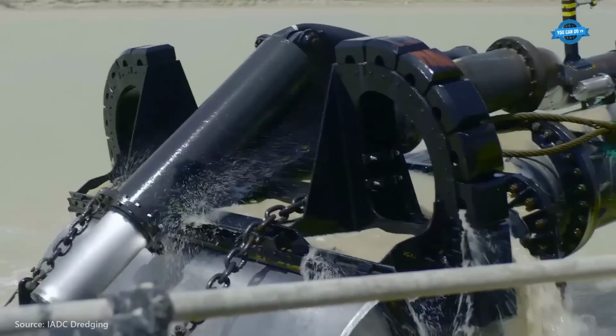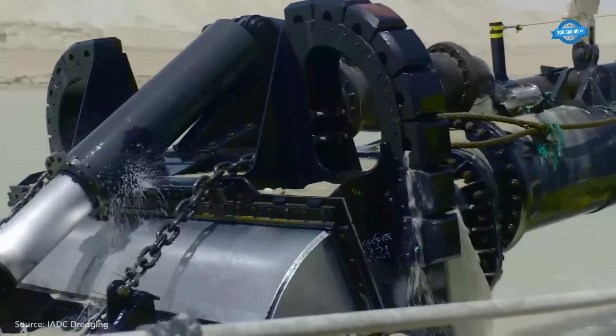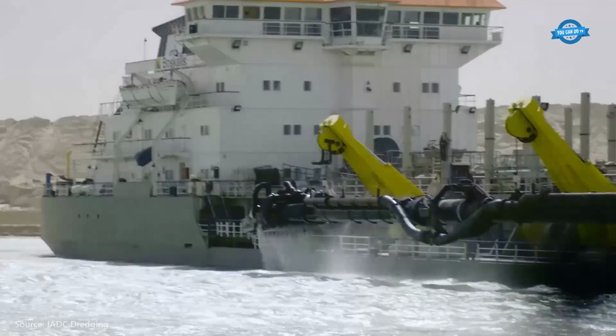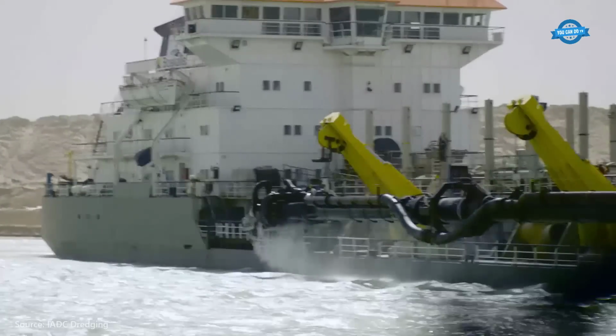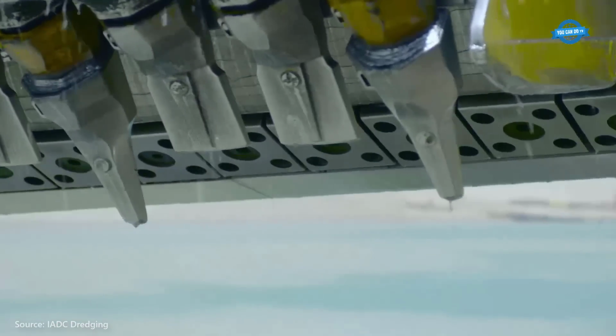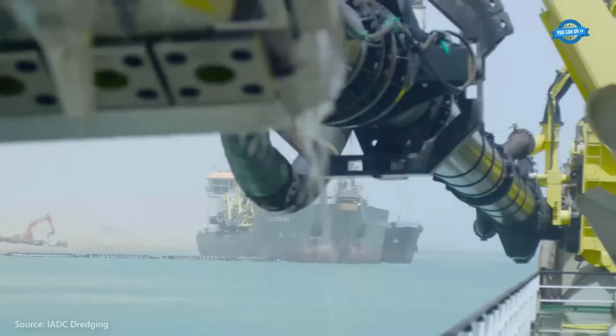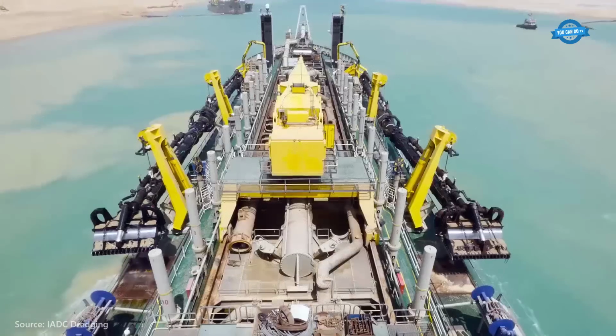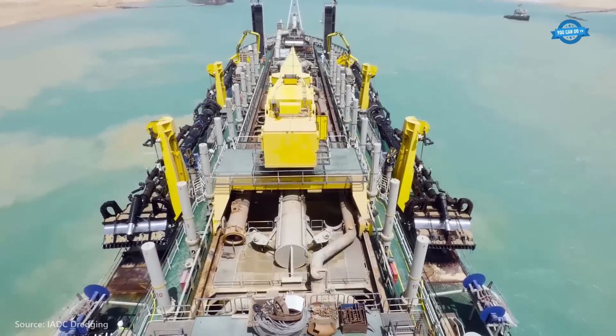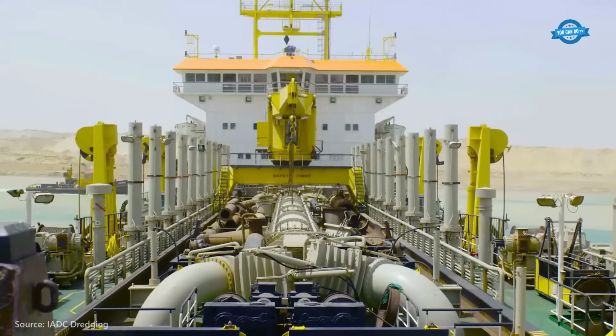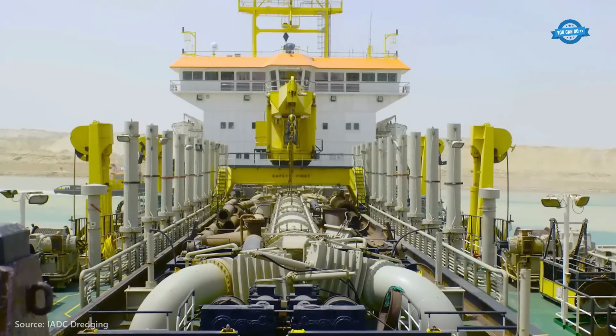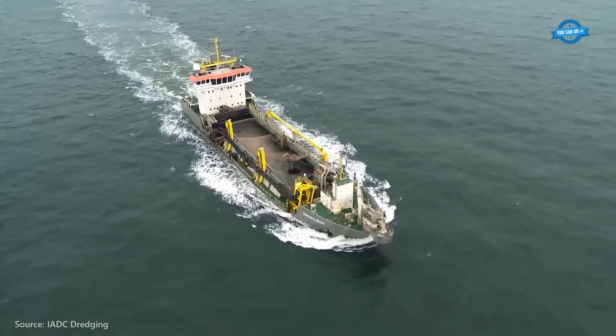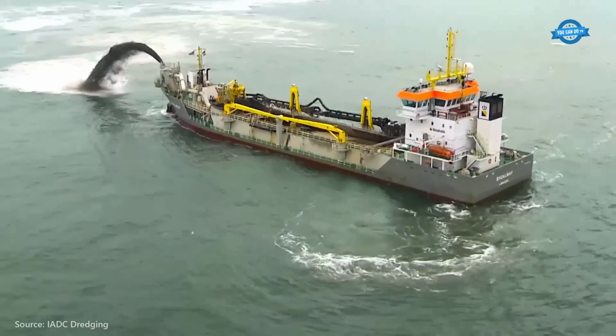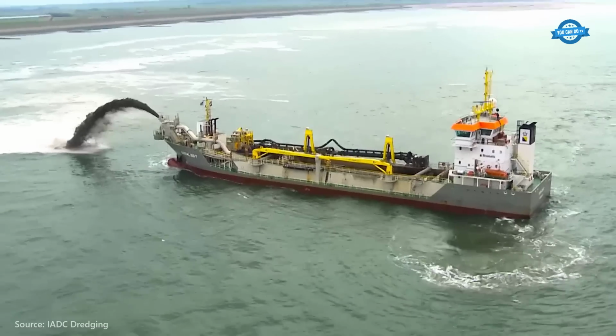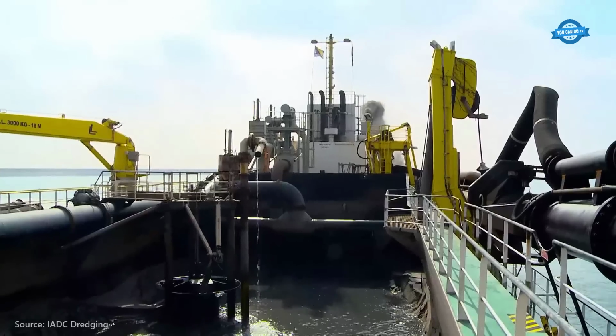Once the hopper is full, the vessel proceeds to the discharge area, where the dredged material is unloaded using one of several methods depending on the project requirements. Bottom dumping is performed by opening hopper doors located beneath the vessel to release the load directly to the seabed. In rainbowing, sand is sprayed in a high arc through a nozzle at the vessel's bow, typically used when the vessel can approach close to the shoreline.